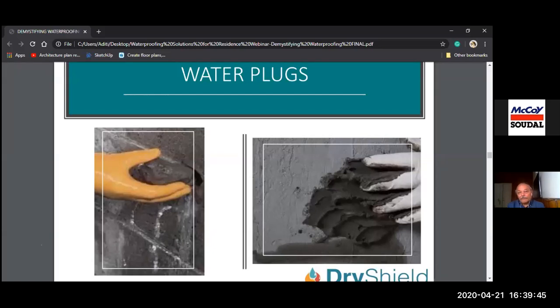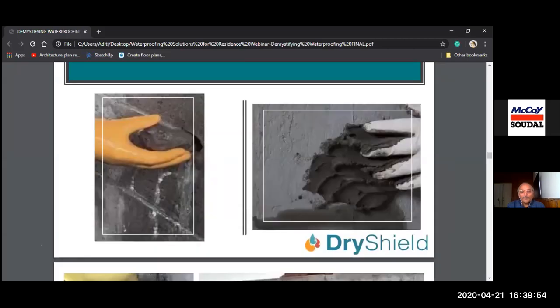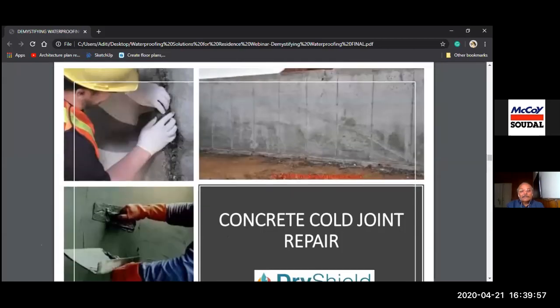This is a very popular product for basement repairs, the crack repairs, especially in new buildings when the structure is still being made. There are a lot of cold joints. You can see in the image on the top right that the plate joints are there. There's one across joint, which must have been due to the concrete being poured in a second stage. And you'll find that there are cracks, that cold joints are there.